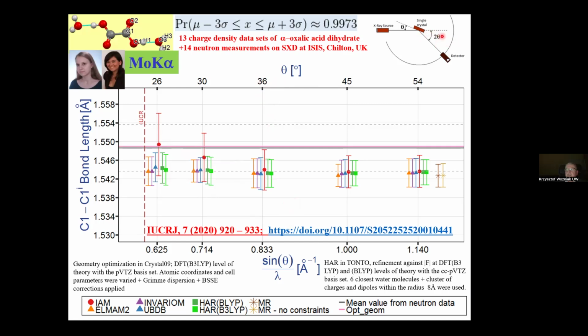36 degree diffraction angle, the results are very much like we are obtaining using other aspherical approaches. But the point is that the IUCr recommendation for Mo radiation is this one. So it should be changed. And we also have reference values from neutron diffraction, because we also got 14 neutron measurements on SXD at ISIS in Chilton, UK. And this red line comes from optimization of geometry in the crystal.